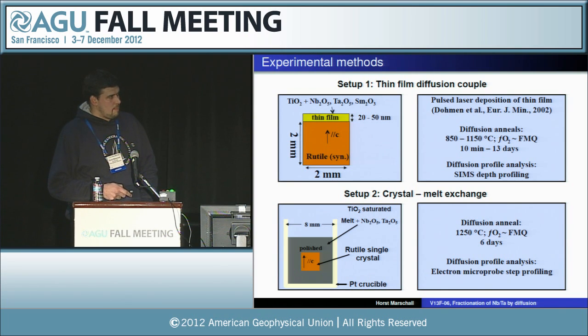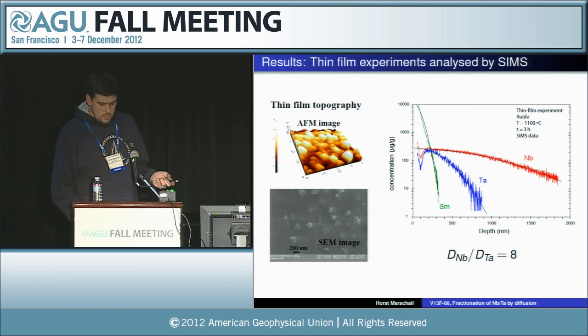The second type of experiment is just dropping a rutile crystal into a niobium tantalum doped glass or melt, and analyzing the product after diffusion, analyzing the product with electron probe stepwise profiling. And this is the result for the ion probe, and it's on the right side here, concentration versus depth, and that is a very striking result, I guess. You have a steep profile for tantalum and a very large profile for niobium, which immediately tells us that niobium is much, much faster than tantalum.